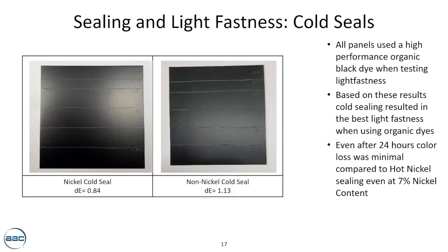Again, the amount of additive in this particular seal plays an important role, as the fluoride content in the seal is higher, and the amount of nickel incorporated with this particular seal is 4 times higher than a hot temperature seal.